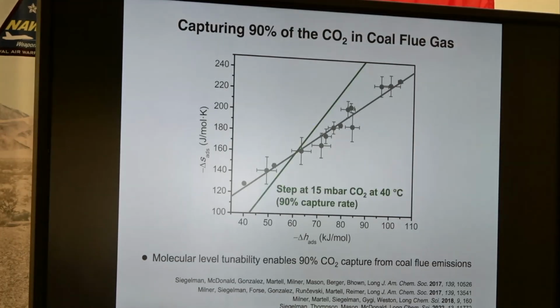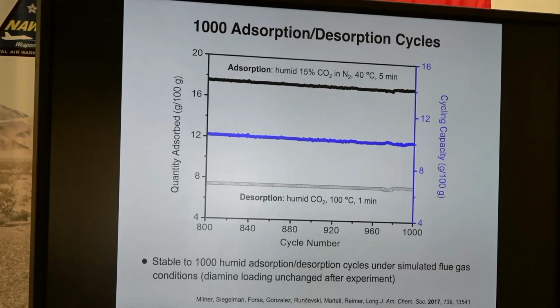And so if you're treating coal flue gas, like in the Petra Nova power plant, you've got 0.15 bar of CO2. And if you want to capture 90% of that carbon dioxide, then you've got to have your step at 0.015 bar or lower. And so that's going to minimize the temperature swing we need to regenerate and release the carbon dioxide. So for capturing from a coal exhaust gas at 40 degrees C, we would choose that particular diamine. And then we can study what happens when we adsorb and desorb CO2 1,000 times.